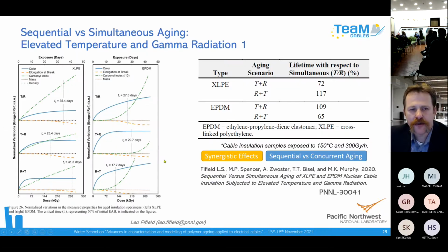Here we go. So we similarly looked at the effect of gamma radiation and thermal stress as a function of the order with which they were applied to the material. We did thermal aging first and then radiation, or the other way around, or we did them simultaneously. And we saw through different measures of aging that the lifetime of that cable material was affected by the order of exposure. Again, the take-home message was we can't say all materials are going to age more quickly when you do it in a certain way. It turned out it was material dependent.